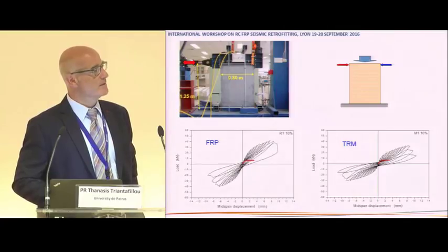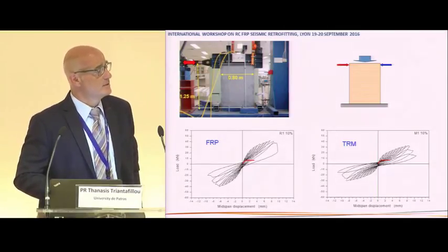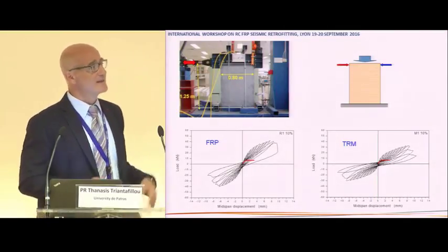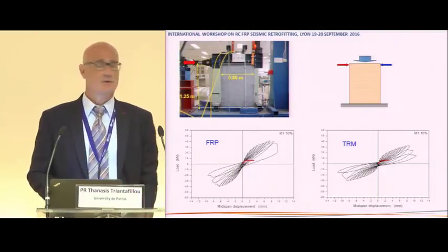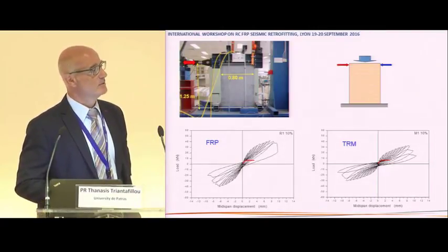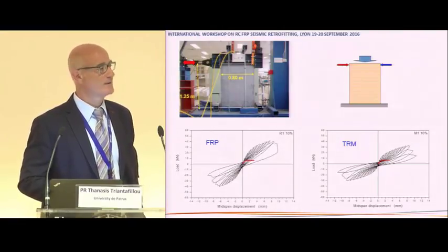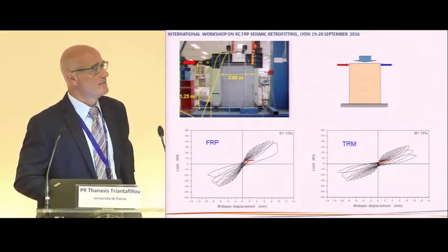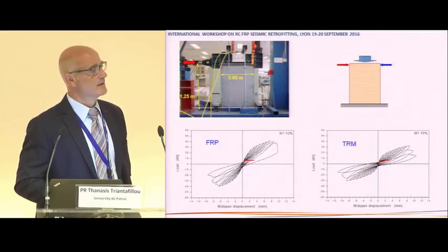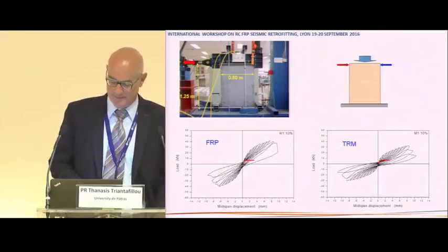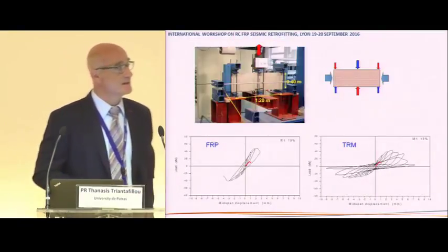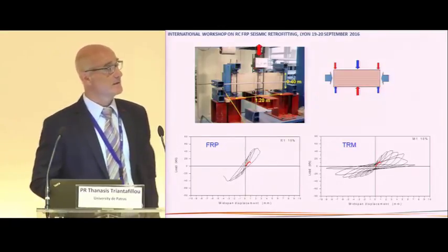If you do strengthening with FRP, let's say with a layer of a textile bonded using an epoxy resin, that's what you would get. If you use the TRM system, that is the same textile bonded with a cement-based mortar, you get a response that is very, very similar. And sometimes the ductility is even higher, as you see here.